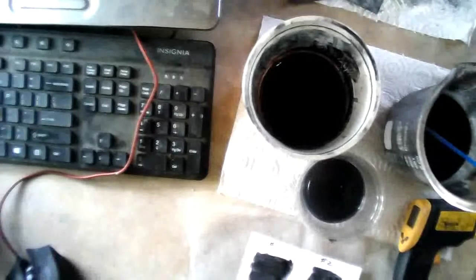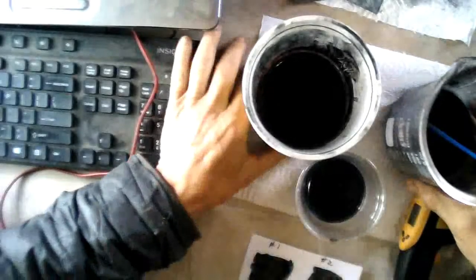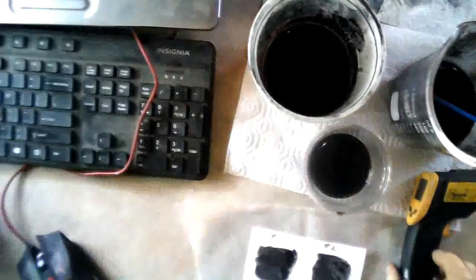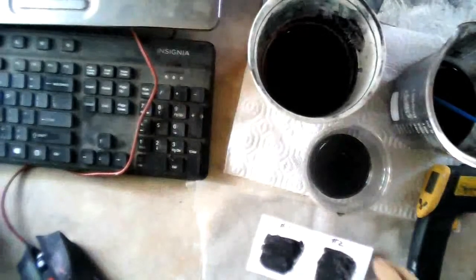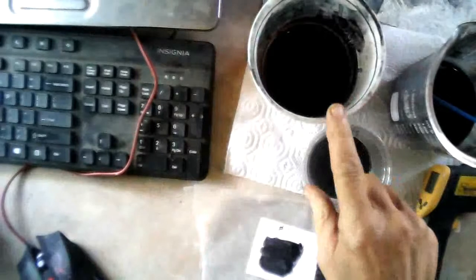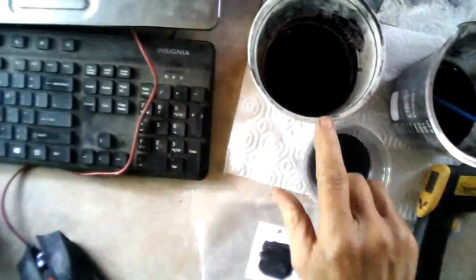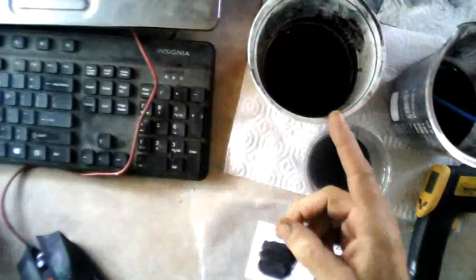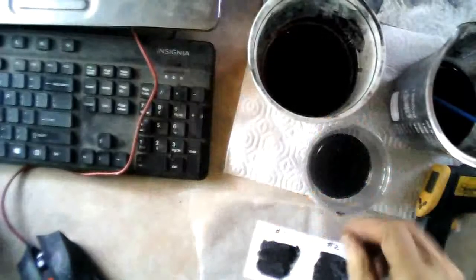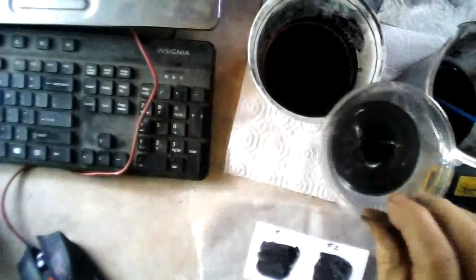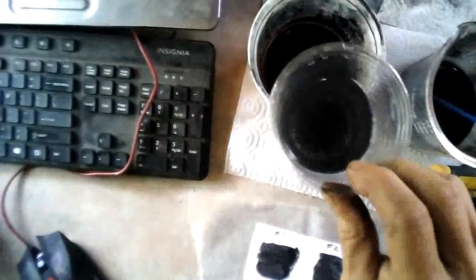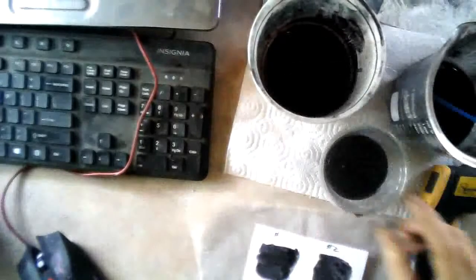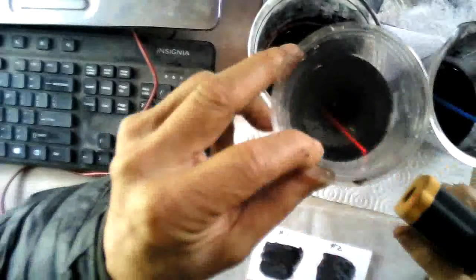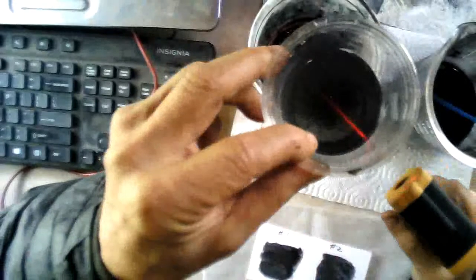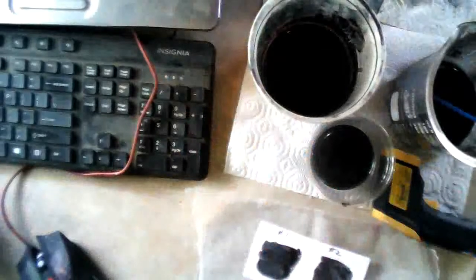Alrighty, I'm back, and I don't have time to build another battery and test it on this video, so I'm going to use the last couple of minutes here just to catch up on a couple of things. This is the first intercalated graphite that I made, and that I redissolved in water and then sonicated, and this has probably had about an hour and a half of sonication so far. I took a little bit of it on a brush and dipped it in this water here, and you can see that there's stuff in there. You can see a little bit of settling out at the bottom too. We're going to shine the laser from this infrared heat gun or thermometer in there. You see the laser shining through that.